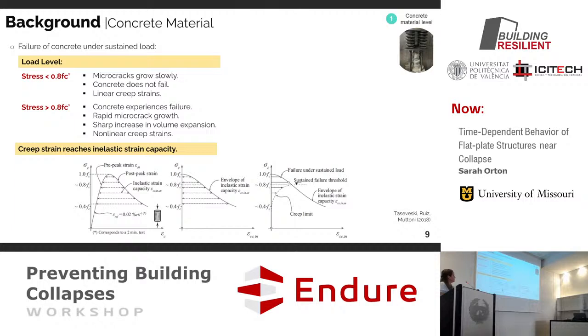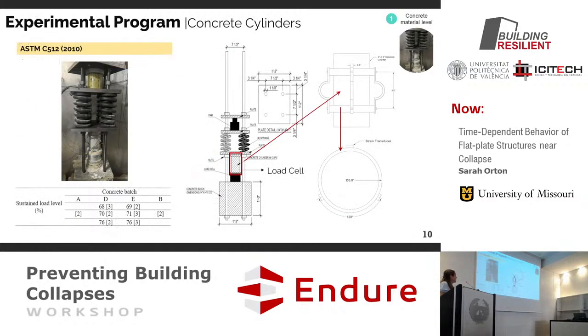strain capacity. So if you look at the compression test curve and say that's what you would get under a standard cylinder test, then you load it up to maybe 80 or 90%, and then you would strain at that level and it would reach failure whenever that strain hit the descending branch of the curve, which I thought was a really eloquent idea, and it works. It's always nice when it works.